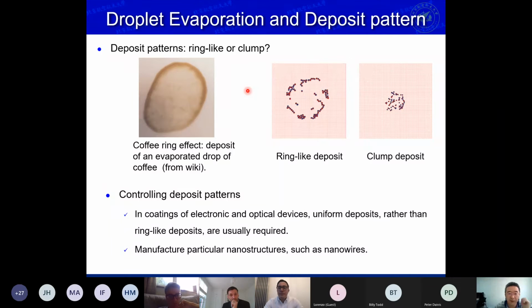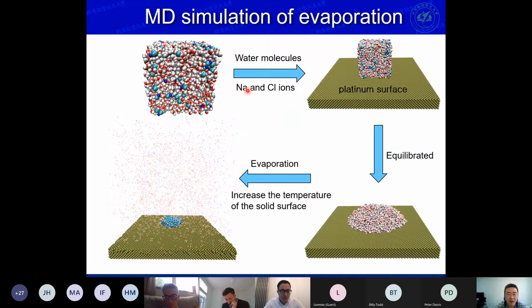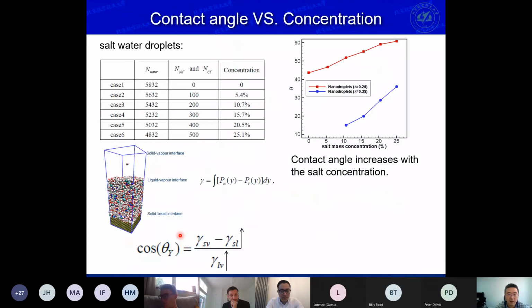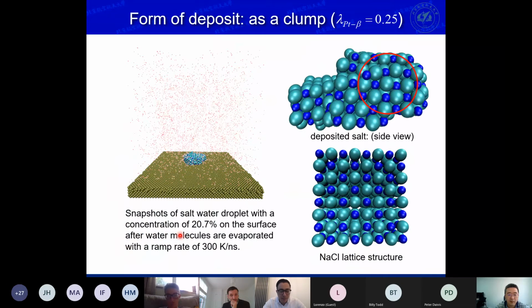Okay. So the last part is about droplet evaporation. We focused on the deposit pattern. I think all of you know the coffee ring effect. Here we do MD simulations of salt water evaporation, because if we increase the temperature of the surface, the water will evaporate and the salt ions will be deposited on the surface. And here I can show some different patterns.